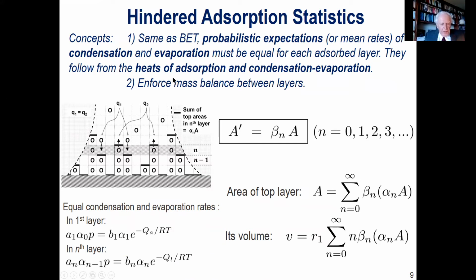They can be solved, but we solve them under a restriction. The restriction is that the surface area in each next layer is decreasing. So you see, we imagine restraints here, given by some function beta of the number of layers. Now, what function? It has to be power law. Why? Because the procedure is self-similar, because after the first layer, there's no characteristic layer which will be standing out. And so it's a self-similar process which requires power law.